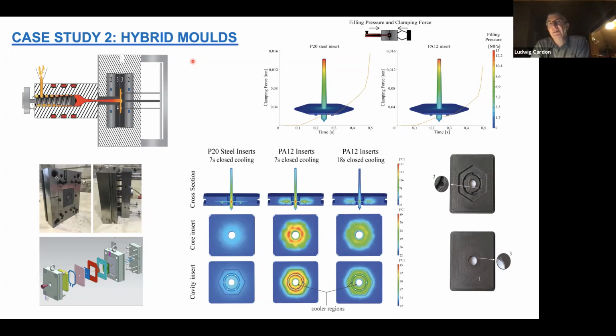But when you have a coating with a kind of lubrication, you can try to avoid somewhat faster wearing, but you will have wearing. But when you then can produce, instead of 3D printing, in this kind of molds the real polypropylene, polyamide, ABS, what you want, then you have a real final material by injection molding. Perhaps not the optimal parameters, but it's possible to do that.